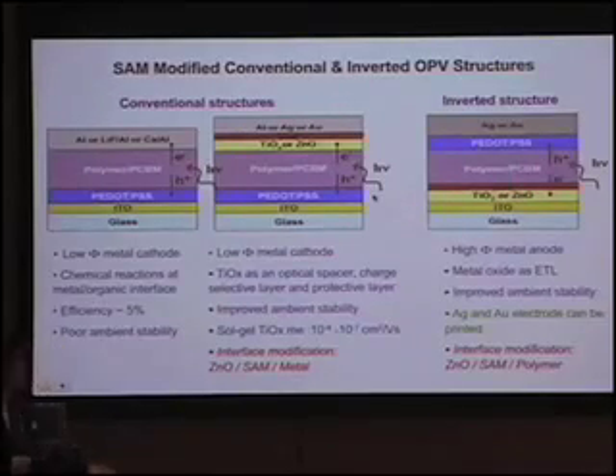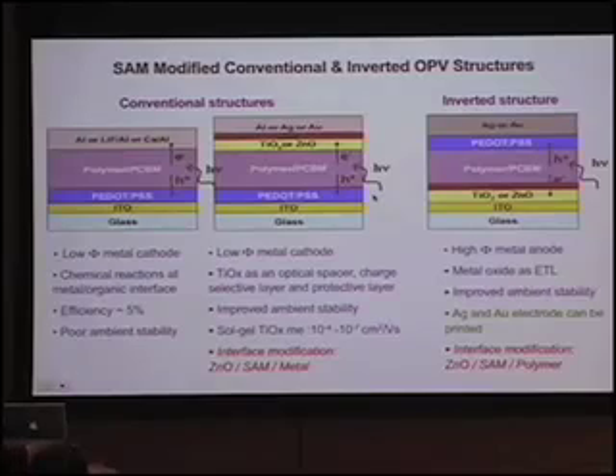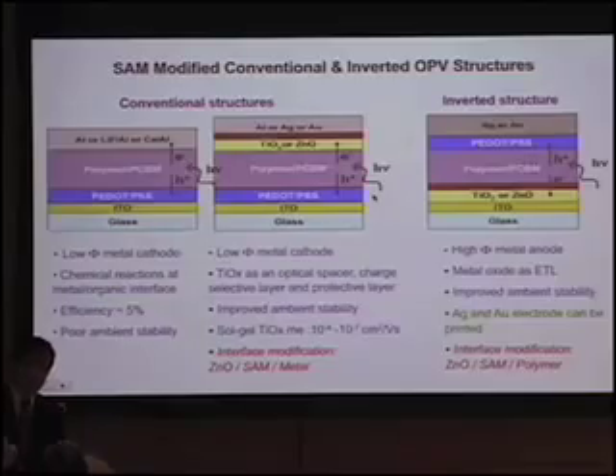Okay, so this is an inverted device structure, right? I take the most sensitive part of my device and embed it, utilizing my glass as a protection layer to protect that. But in order to do that, you need to effectively collect electrons through this direction, right? So my self-assembled monolayer on top of this, either titanium oxide or zinc oxide, all those are very good electron transport layers, metal oxide for electron transporting. So electron transporting through that is no problem, and they can be collected by ITO.